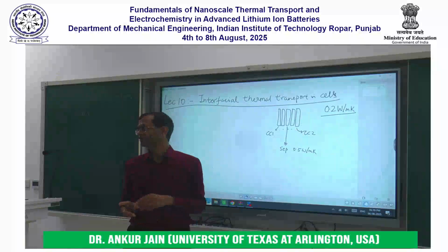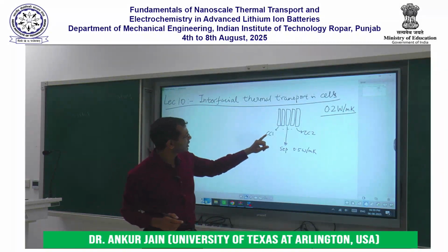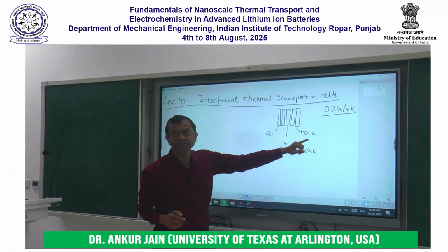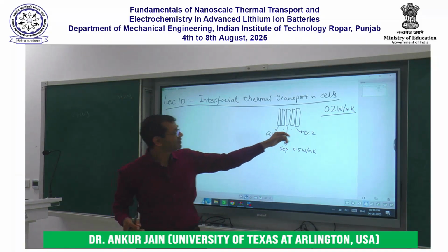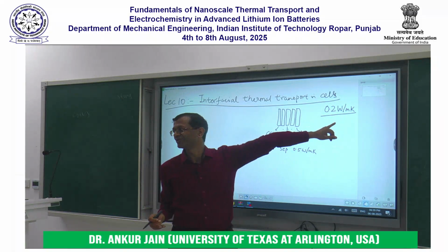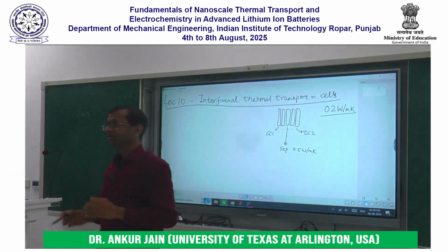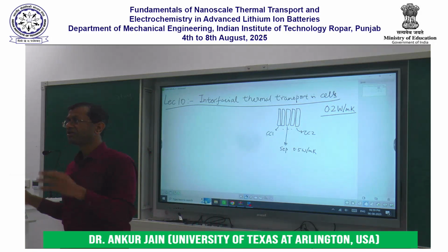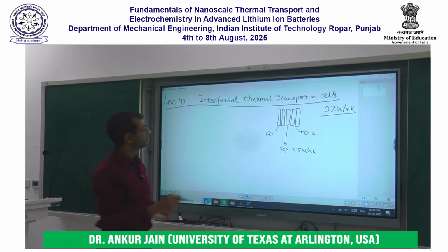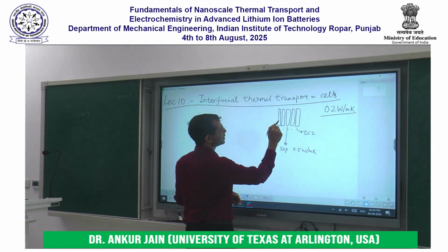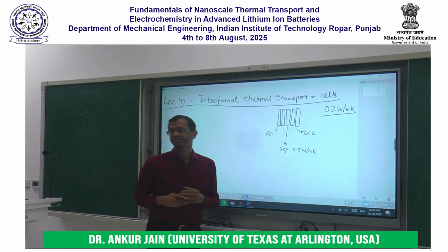an important role. Because if I just combine the thermal conductivities of these materials alone, it will not give me a value as low as 0.2. The reason why all 5 of these, when put together, perform even worse than the worst one is that they are not talking to each other. The heat has a very difficult time jumping from one material to the other.